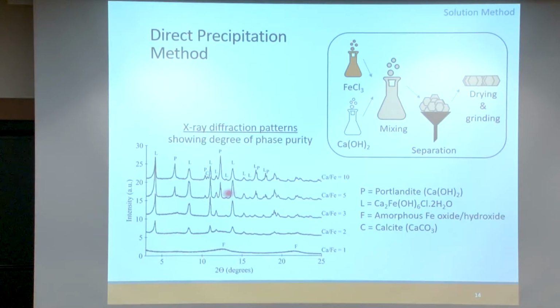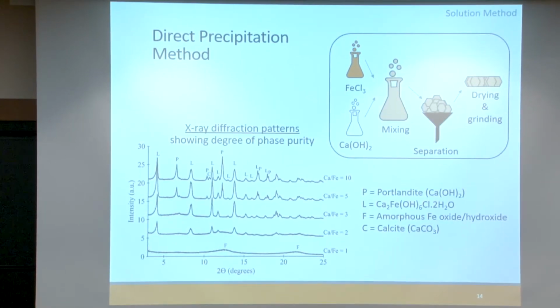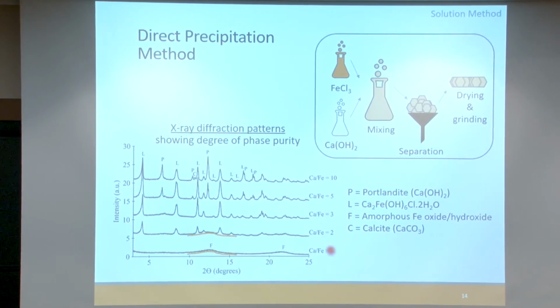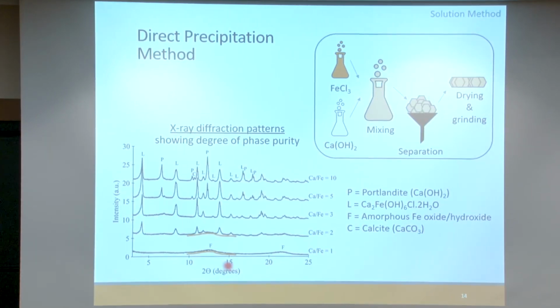And so we can characterize what we synthesize using a technique known as X-ray diffraction. Essentially, we can look at this and get an understanding of what phases are in there. What we see here is if our starting ratio of calcium to iron for those solutions is 1, we don't end up with any of the peaks that have the L on it, which is indicative of the layered double hydroxide. We only end up with an amorphous iron oxide hydroxide type phase.